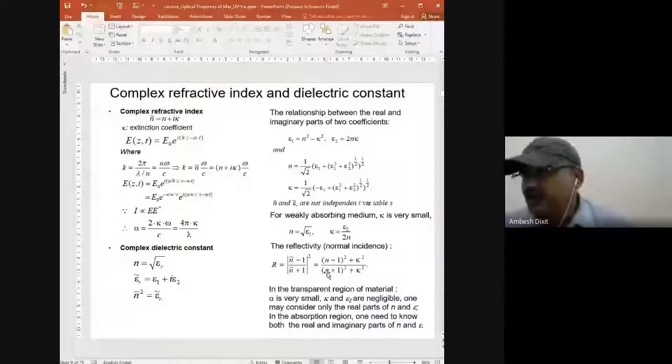Up to this point, whatever we have, similarly we can define transmittance with respect to normal incidence, and then define transmittance as a function of n and k. So you can measure transmittivity as well, and from the transmittivity you can find n and k by fitting that data. Otherwise, you have two sets of data, R and T, and you can compute from one and test on the other, to see whether they are fitting properly.